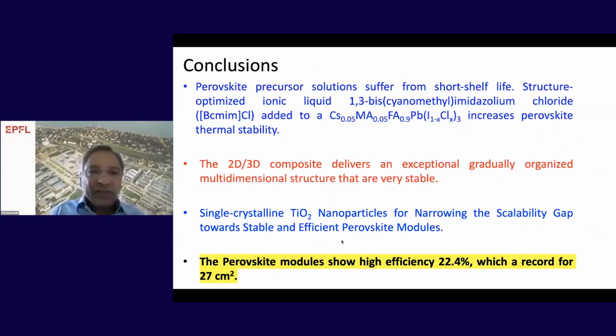With this, I would like to conclude my presentation. The ionic liquids are important to stabilize the perovskite composition. The 3D/2D interface engineering is important to enhance the hydrophobicity and increase the stability of the perovskite layers. Single crystalline TiO2 nanoparticles help narrow the scalability gap towards stable and efficient perovskite modules, as I showed you in the data. The perovskite module shows high efficiency, 22.4%. This is our lab. This is still the record for the 27 centimeter square.